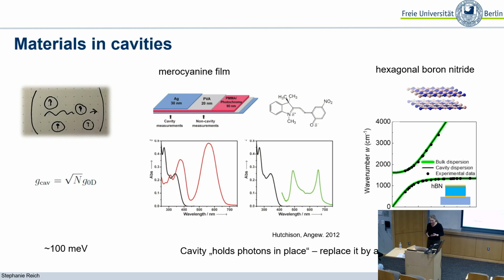So we looked at these things, and what we started to ask ourselves is whether it still makes sense to use cavities for these kinds of experiments. Because originally we had the cavity there to keep the photons in place so that they interact longer with a single molecule. But if you consider an infinite crystal, then your photons are going to be inside and will also perfectly overlap with the material. So there's actually no need to resort to a cavity in order to increase light-matter coupling. You're not achieving very much with that.